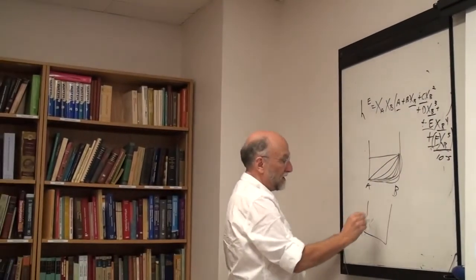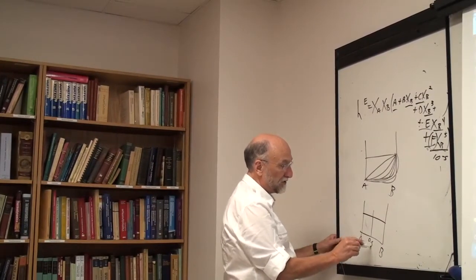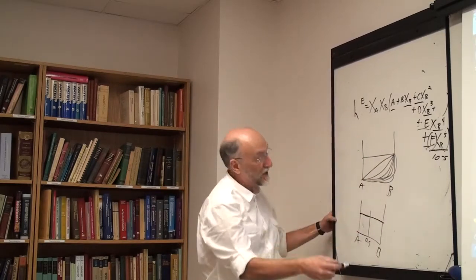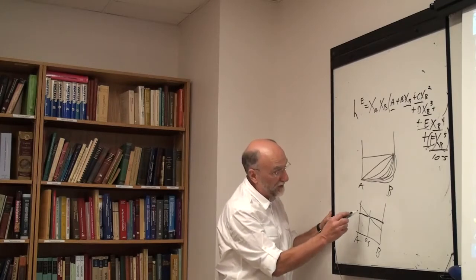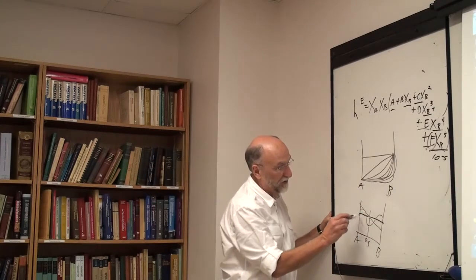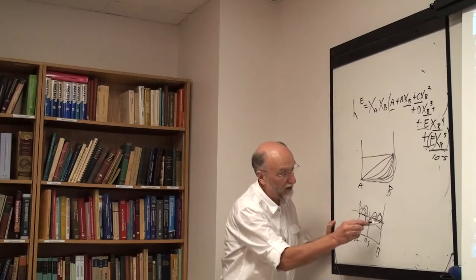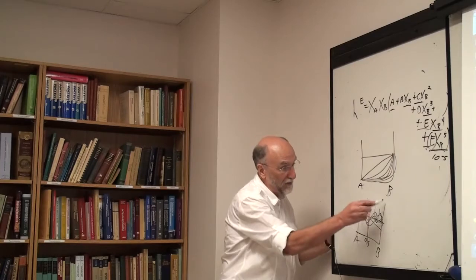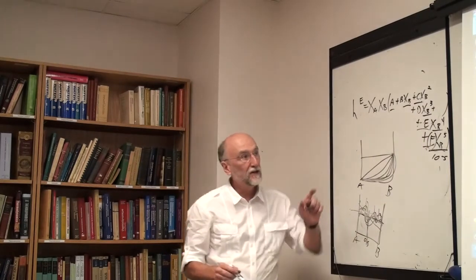But if I plot a and b and my Redlich-Kister terms, there's your constant term, of course. The first term, xb minus xa, goes through 0 at 50%. The second term looks like this, the third like this, the fourth like this. They're all more or less symmetric around 50%, and they don't all have a maximum at one composition and a minimum at another.